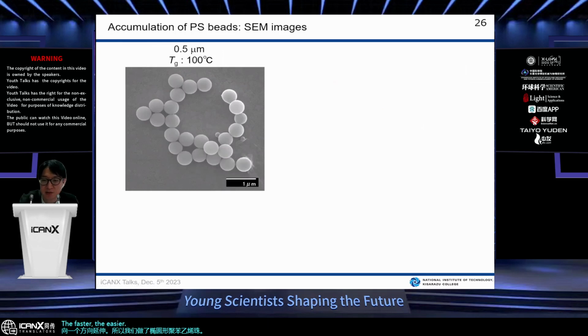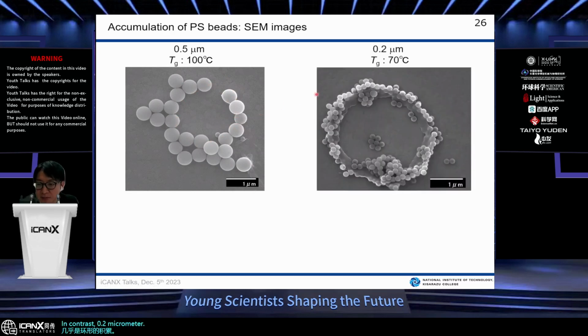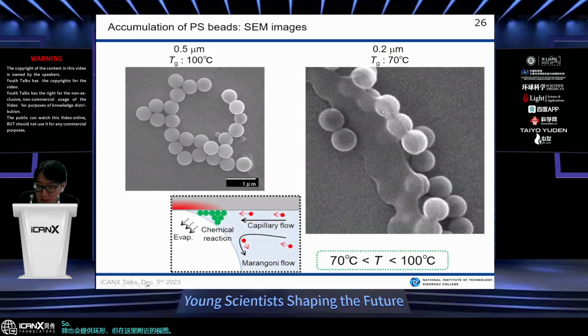The first result is shown here, the accumulation of polystyrene bead SEM image. The 0.5 micrometer polystyrene beads provided an almost ring-shaped accumulation. In contrast, 0.2 micrometer polystyrene beads also provide a ring shape, but in the close view around here, the polystyrene beads are a little bit melted and in contact. So from this result, we estimate the temperature heated up around this space is 70 degrees Celsius to 100 degrees Celsius.